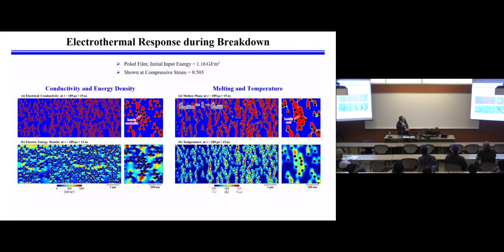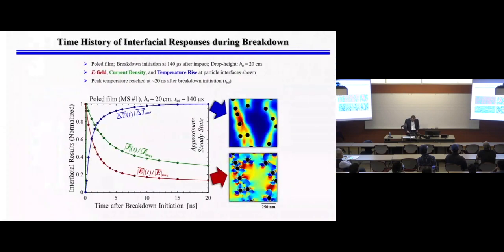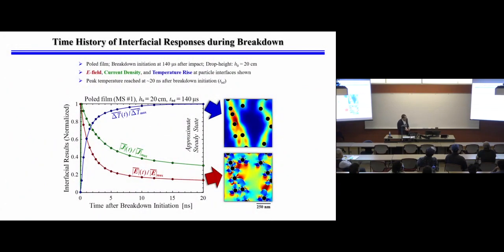Now, the conductivity: initially, before breakdown, there is no conductivity. There are no areas that are conductive, but the breakdown causes conduction to occur. So those are the areas that have become conductive. But once they become conductive, they have heat, the current flow, and then the temperature increase spreads into other areas also and causes melting, even going beyond the areas that have broken down. So that all is tracked. And this just shows how quickly things happen, right? This is nanoseconds. Once the breakdown begins,